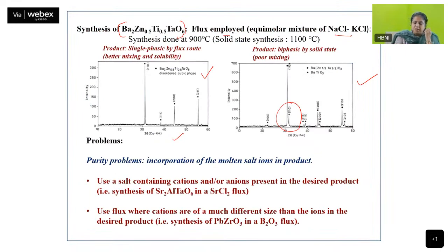Okay, the problem is sometimes the ions of the flux can get incorporated in your material. How can you get out of it? Choose a salt that has a cation or anion present in your product that you want. For example, if you want to synthesize this, now this is strontium. Choose SrCl2 flux. Okay, common ion. So even if it goes in, it doesn't really matter. Or you use a flux where the cations are much different in size than your reactants. For example, you want to synthesize this. Both lead and zirconium are bigger ions. Choose B2O3 flux. Boron is very small. It won't go into your material.